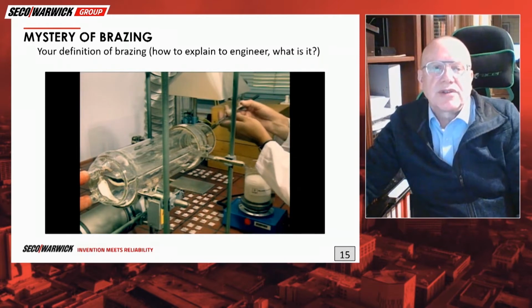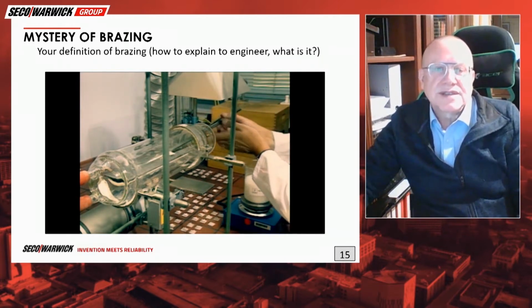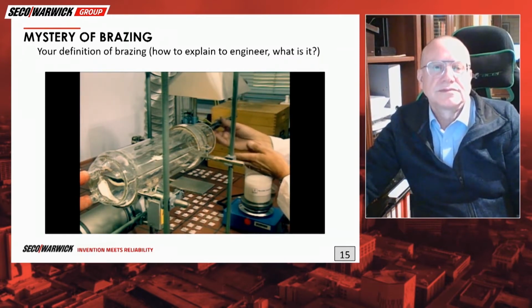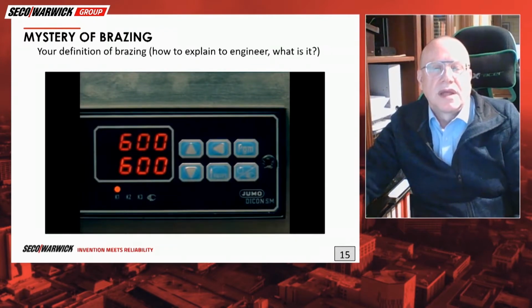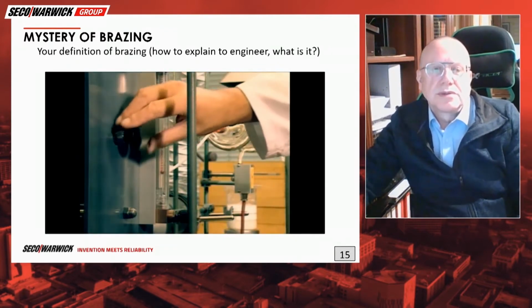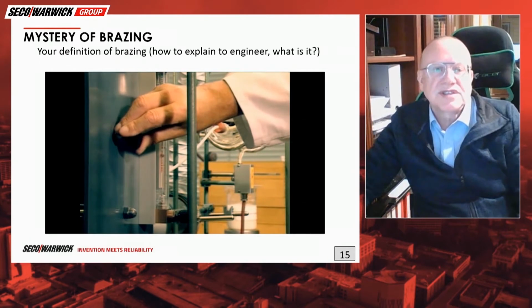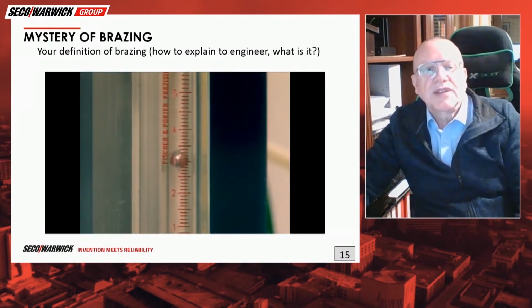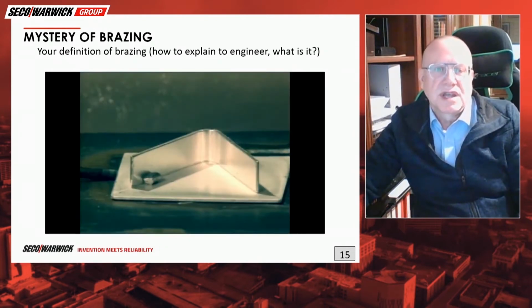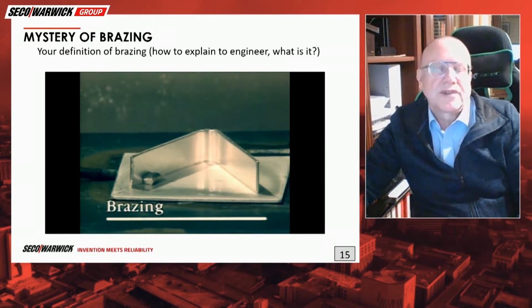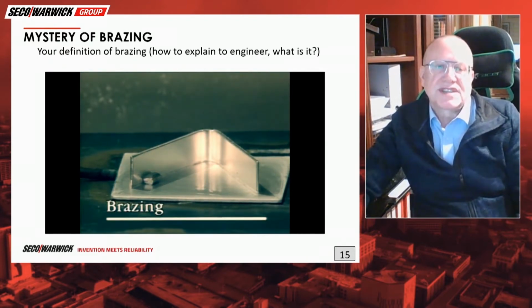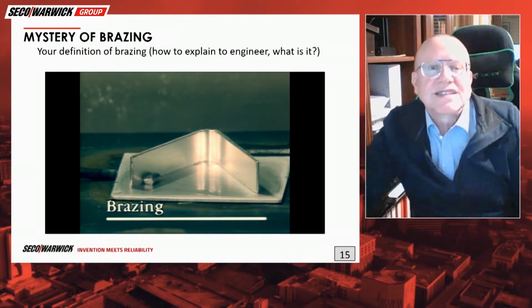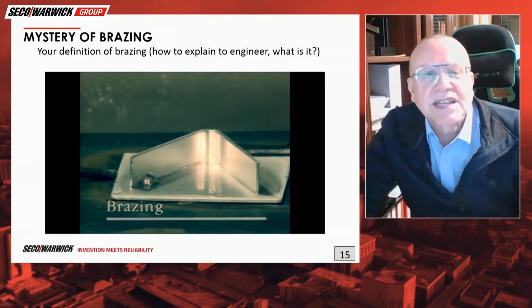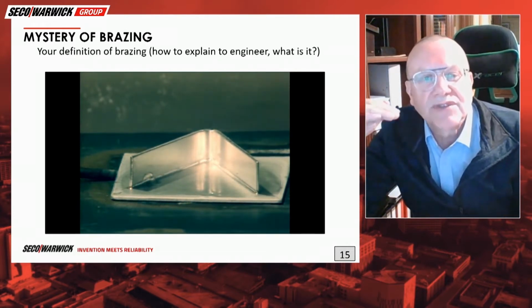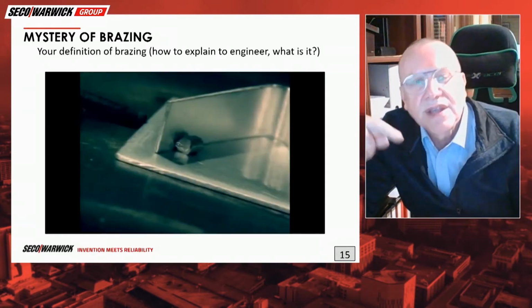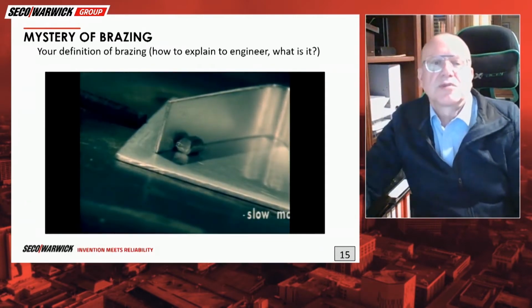We put the whole assembly inside the furnace. We set the temperature, which in the case of aluminium is 600 centigrade, and we run nitrogen through the furnace. It is important to have an inert atmosphere inside. Now the flux has melted and it started preparing the surface. Now the filler alloy melts and it flows, it forms a joint.